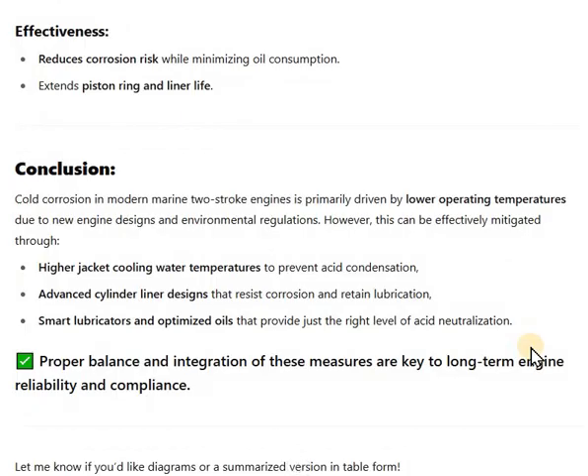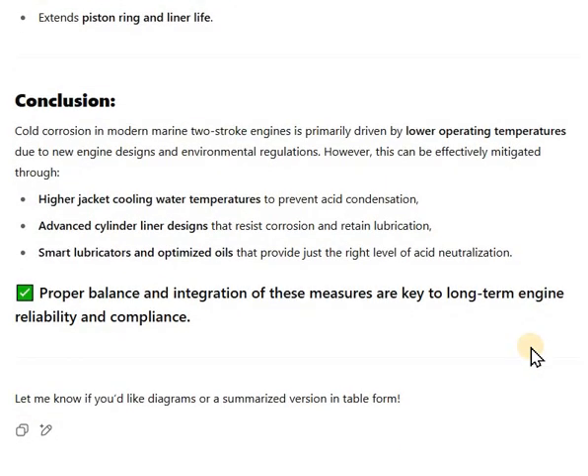And the conclusion that can be drawn here is that cold corrosion in a modern marine two-stroke engine is primarily driven by the low operating temperatures due to new engine designs and environmental regulations. However, this can effectively be mitigated through higher jacket cooling water temperatures to prevent acid condensation, advanced cylinder liner designs that resist corrosion and retain lubrication, smart lubricators and optimized oils that provide just the right level of acid neutralization. Proper balance and integration of these measures are key to long-term engine reliability and compliance.